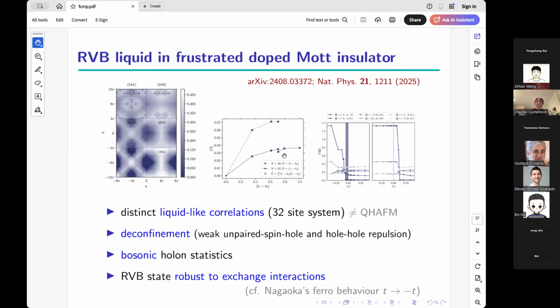There is something else very interesting that we learned from this. If we do the hole-hole correlation, or consider a single hole and a leftover spinon that I was mentioning earlier fixed somewhere in the system, and we look at the hole-spin correlator, they are exactly on top of one another. The hole-spin are the dots, and the hole-hole are the x's. And you see that they overlap perfectly. And if you have a tight binding problem where distinguishable particles and indistinguishable particles have the same correlations, the most likely chance is that the indistinguishable particles are actually bosonic.